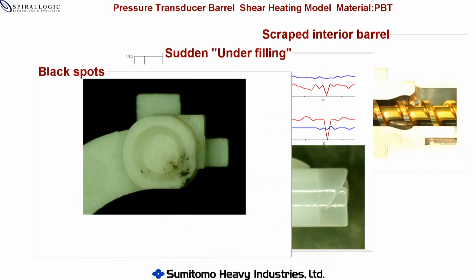Another typical problem is black spots in the products. This is especially troublesome molding transparent or light-colored parts. The cause of the carbonization is also difficult to define. Some may say the material additive degrading or the powder from pellets can burn black. But what is right?